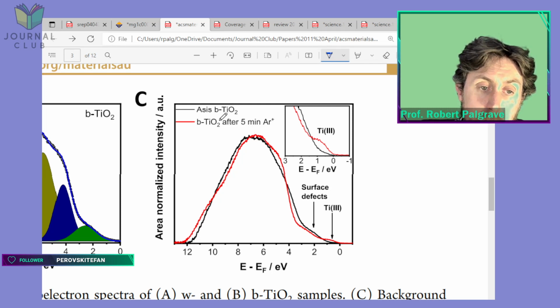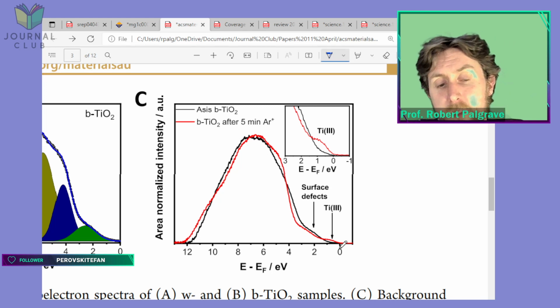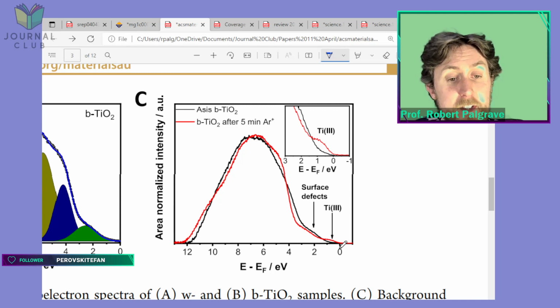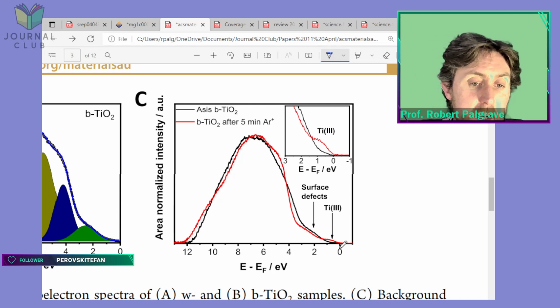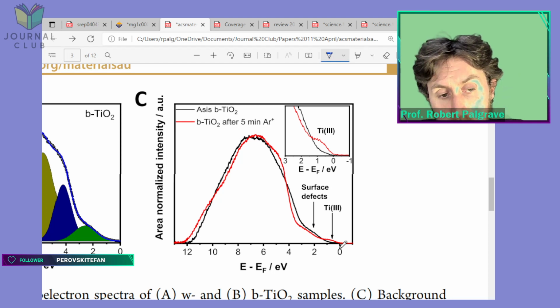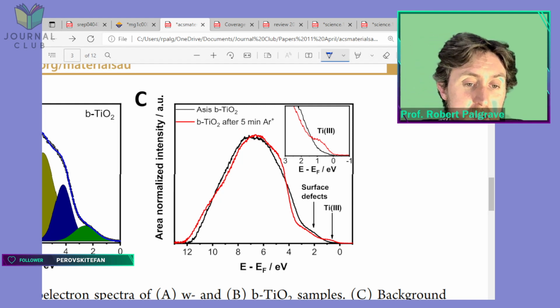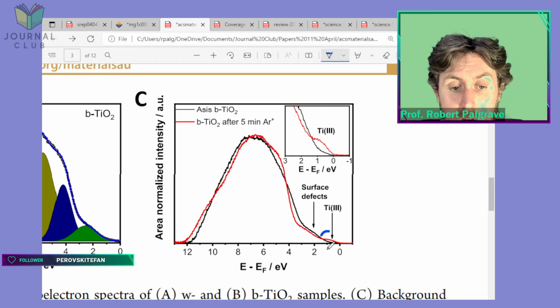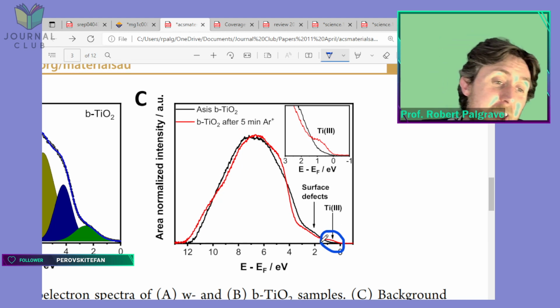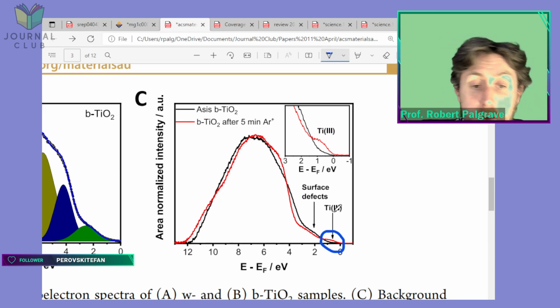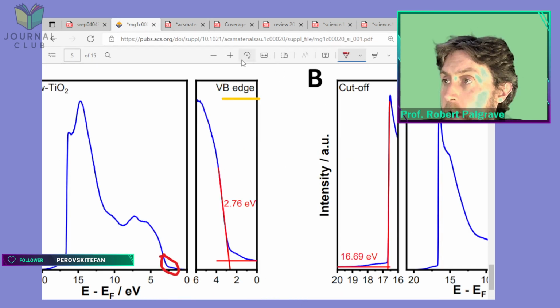original black TiO2, and then after argon ion sputtering. So they're using this argon ion sputtering. It's interesting to use. I think I was originally kind of skeptical that you're just forming Ti3+ through the argon ion etching. In fact, I'm a little bit skeptical about that still. What I would have liked to see here, so their argument is after the argon ion sputtering, you get this Ti3+ environment down here, which has emerged. But the thing is, even when you sputter white TiO2, you get Ti3+. They showed that in their XPS. Yeah, they showed that back here in their supplementary information.